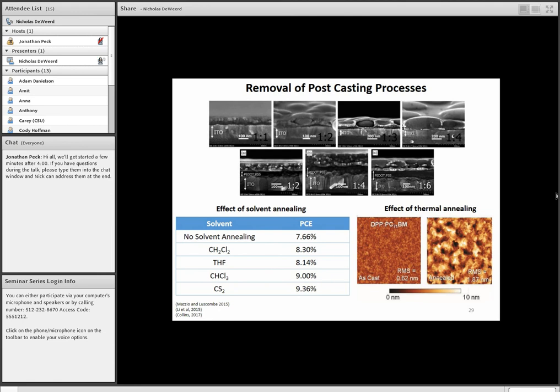Now, on the research scale, these processes are fine. You can see that they do have a rather dramatic effect. On the left, you can look at the solvent annealing process. That's basically when you take your bulk heterojunction device and you place it in a chamber that has a saturated vapor pressure of whatever high vapor pressure solvent you're using to solvent anneal your device. And that's just to allow the molecules a little bit more flexibility to approach the exact morphology that is the highest efficiency morphology. So that would be the most conductive with the highest fill factor and things like that. So you can see it makes a pretty dramatic effect in terms of the PCE values.